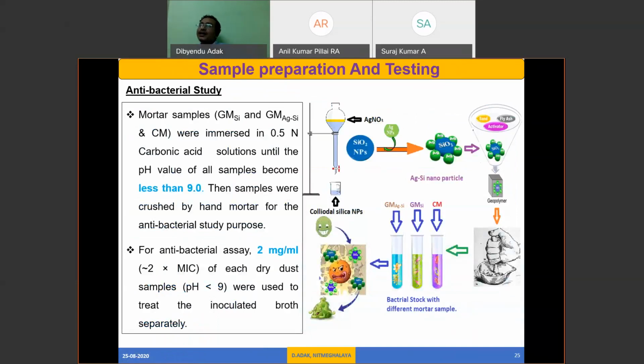As we know, at the initial stage the pH value of the concrete mix is about 12 to 13. At a high pH, or at the early age of the structure, we cannot see corrosion or any bacterial attack on the concrete, because these bacteria cannot survive at high pH. So we have to wait a long time until the pH value becomes lower. But on a lab scale, this will be time consuming.